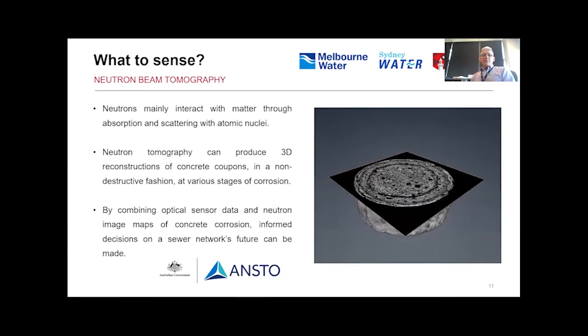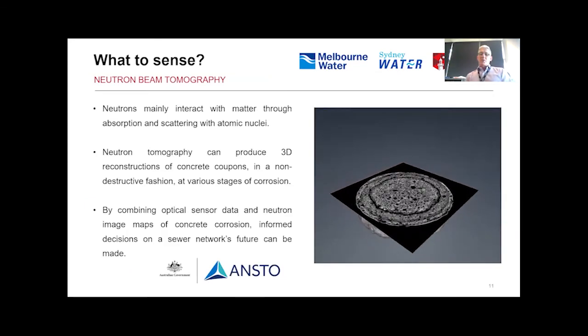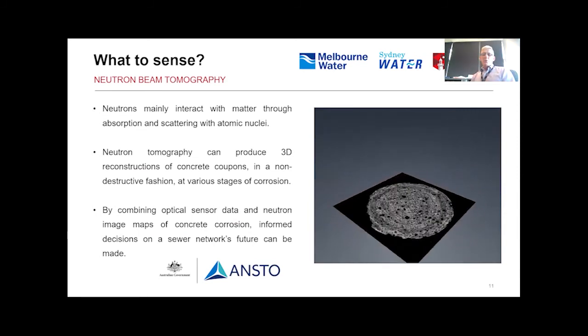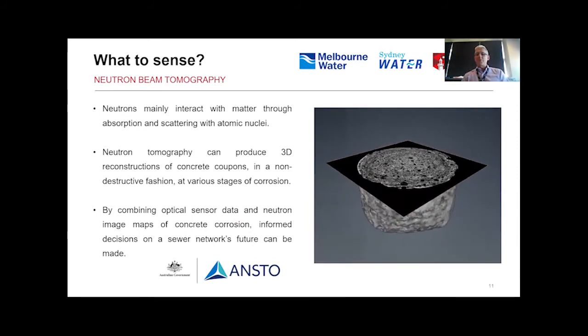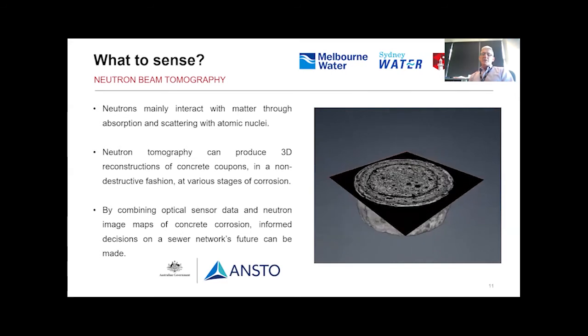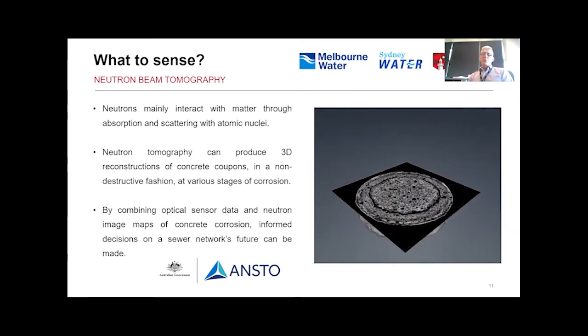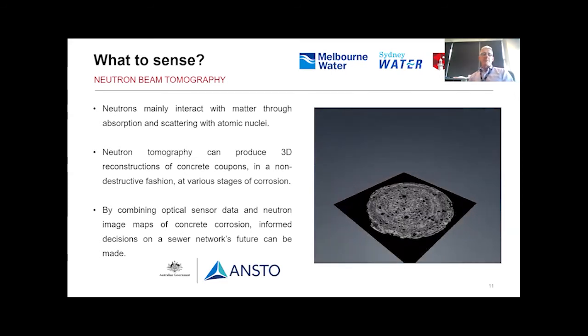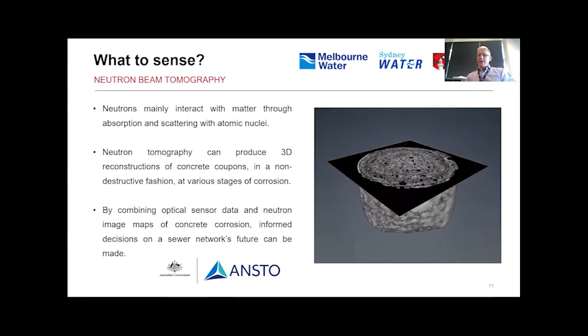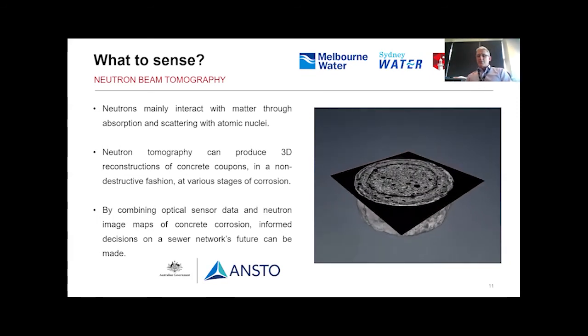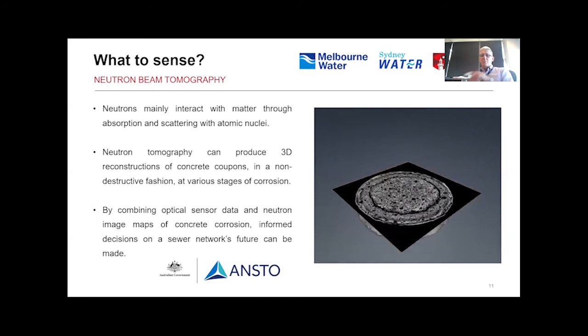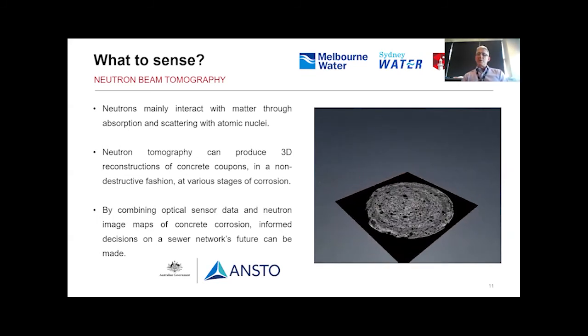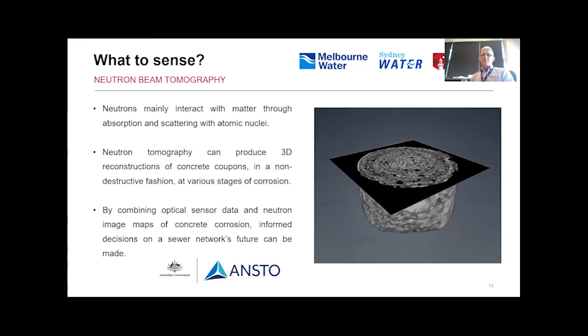Now we also have to know what we want to sense, particularly in the concrete. So we've done a lot of work with ANSTO doing neutron beam tomography on concrete samples that we put through accelerated aging, accelerated acid corrosion tests. And as we scan through this concrete block in that animation there, you'll see this sort of black ring appear a few millimeters inside the surface of that cylindrical section.